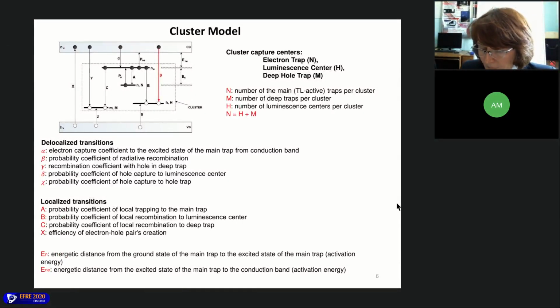In the figure, you can see a scheme of the charge carriers transitions between different energy levels. The main feature of the model is the presence of so-called localized transitions between energy levels contained in the same cluster: transitions A, B, and C. The presented model belongs to the class of kinetic models proposed for the first time by Mandowski and developed by other authors, for example, Pagonis and Horowitz. Such models consider the main active trap as two energy levels, ground and excited states. Also, possibility of electron transitions directly from excited level to luminescence center is assumed, transition B.